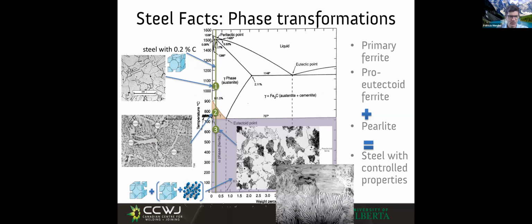So this microstructure is quite complex, but what I want to draw your attention to is how we have the ferrite, and this marks the boundaries, the grain boundaries of what used to be austenite. This is what is called primary ferrite, because we are having austenite, and as we cool down, ferrite appears. We call that primary ferrite.